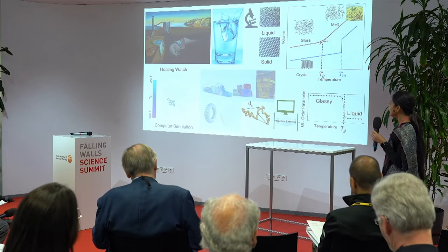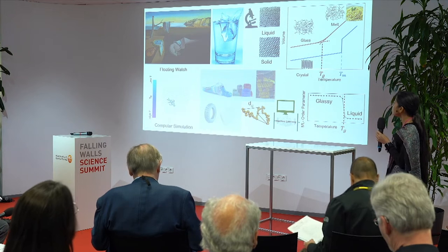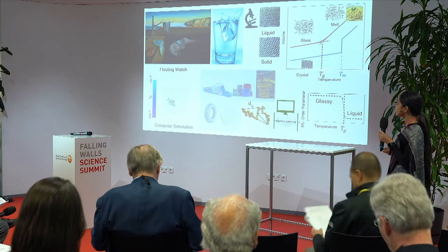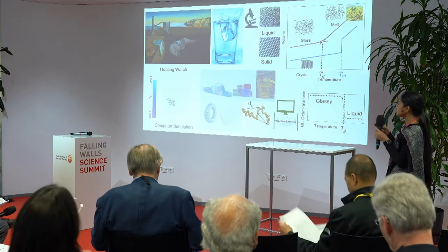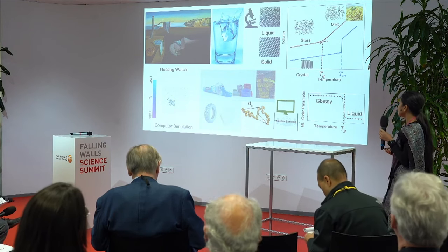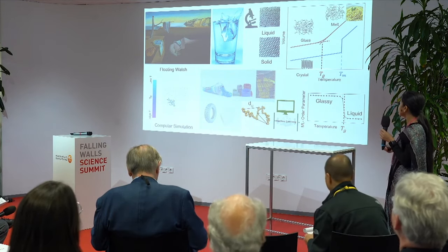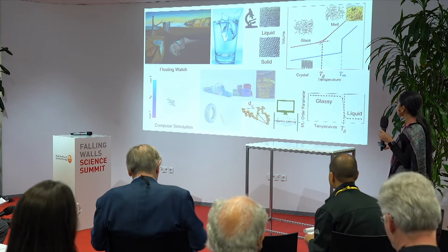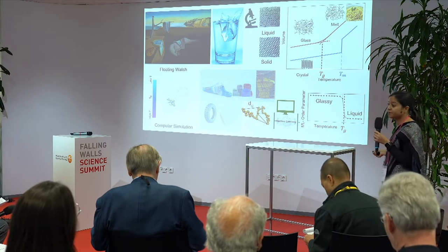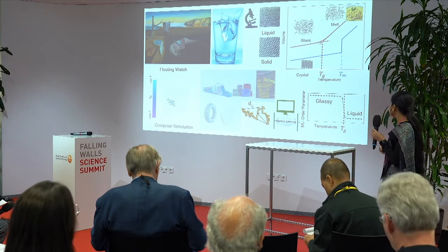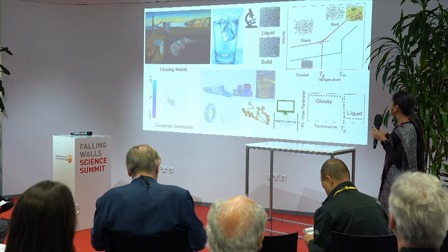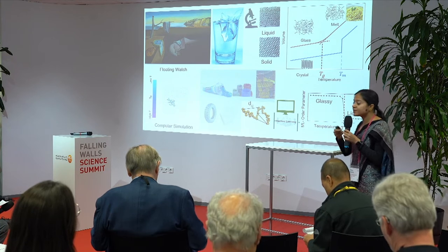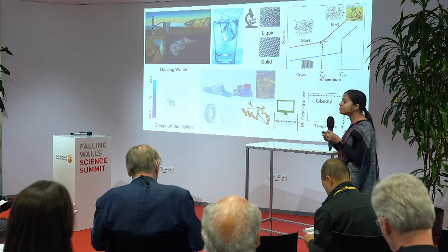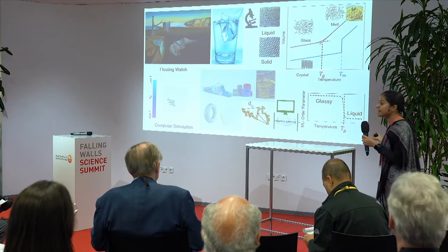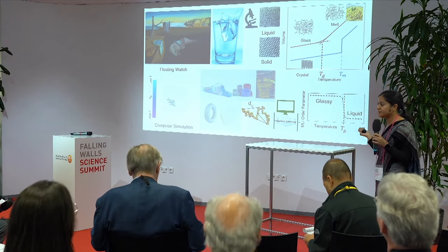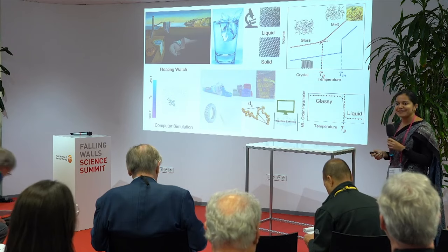by combining molecular dynamics simulation and machine learning models, where we identify the structural fluctuation of each monomer distance and get an order parameter which separates the melt state from the glassy state in a much sharper way. So we get a Tg which is much sharper than the conventional method, and we use the microscopic distance as our input descriptor to identify a macroscopic property like the glass transition temperature. So that's all. Thank you very much.